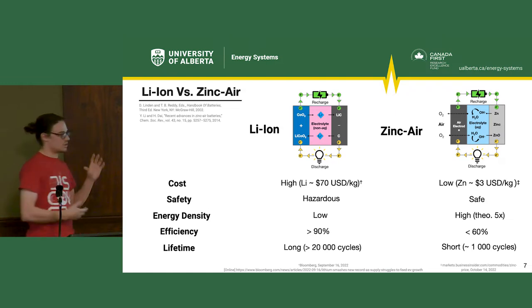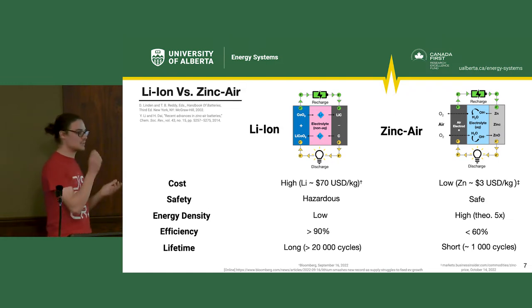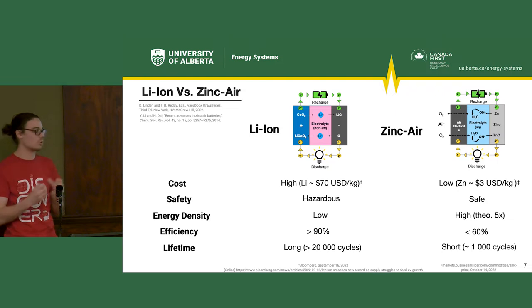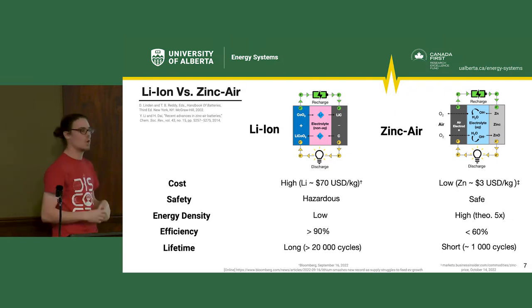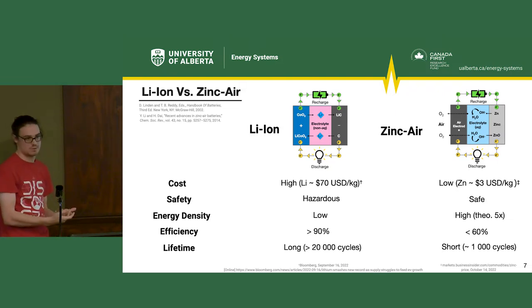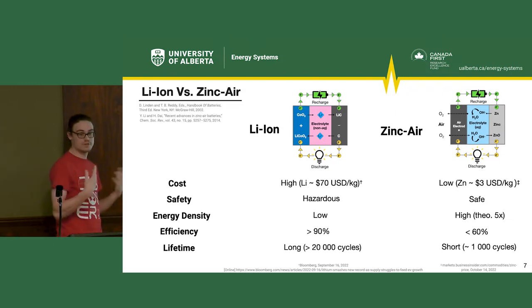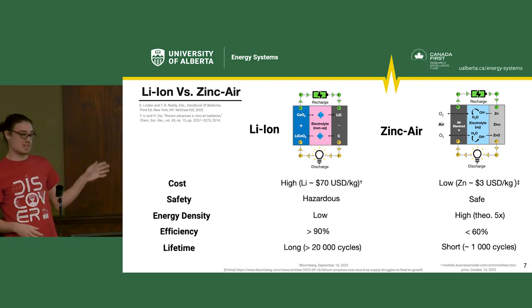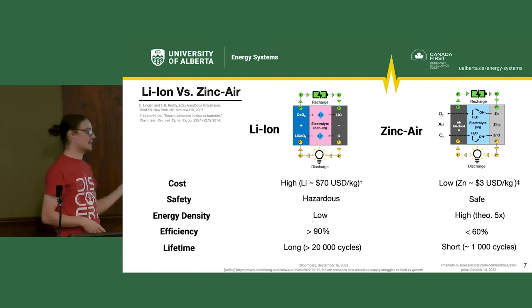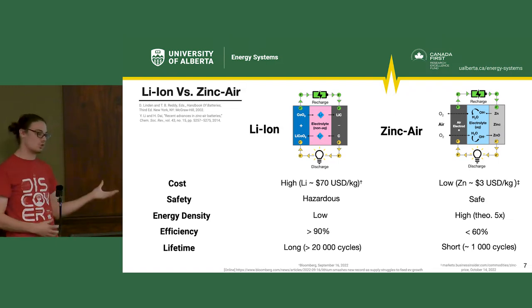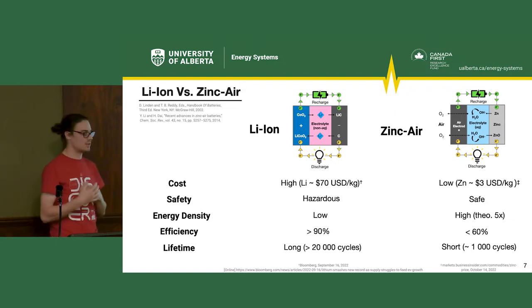Now, I mentioned there's a lot of good positives with zinc air, but because the reactions are big chemical reactions, not just a simple back and forth, it's a bit more difficult for it to happen. So we have energy losses. So that efficiency value is more along 60% for zinc air versus greater than 90 for lithium ion. So that's one of the drawbacks, what we're working on right now in zinc air batteries.